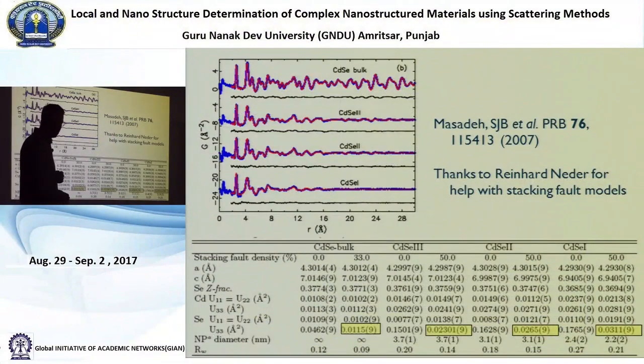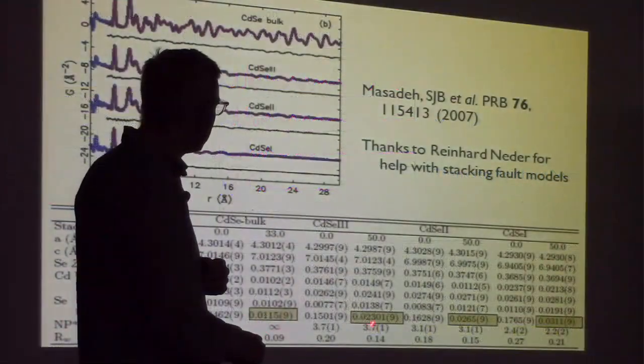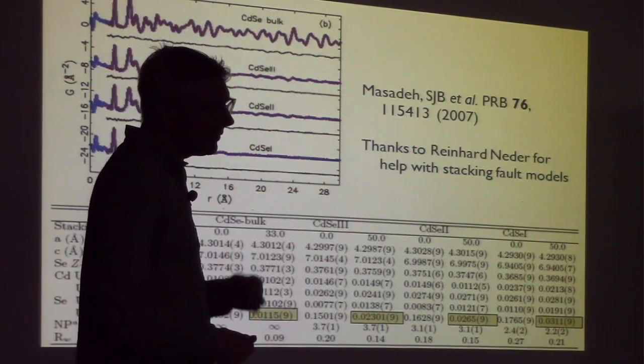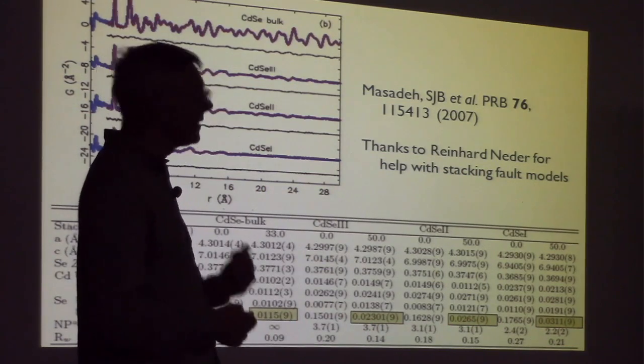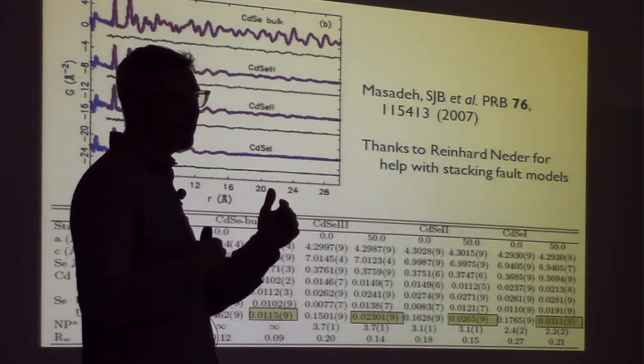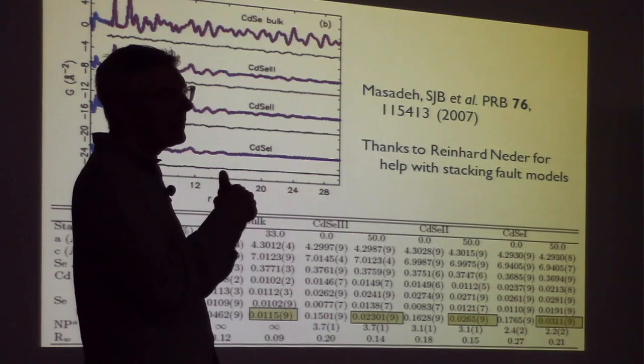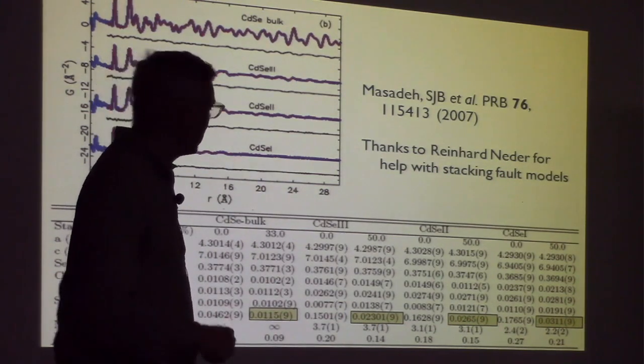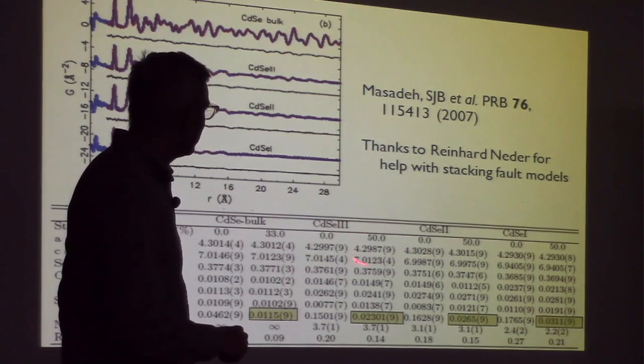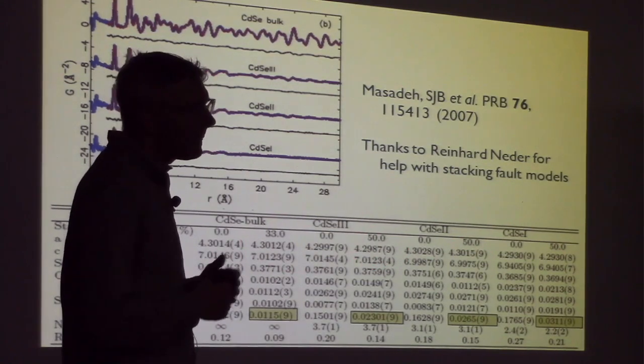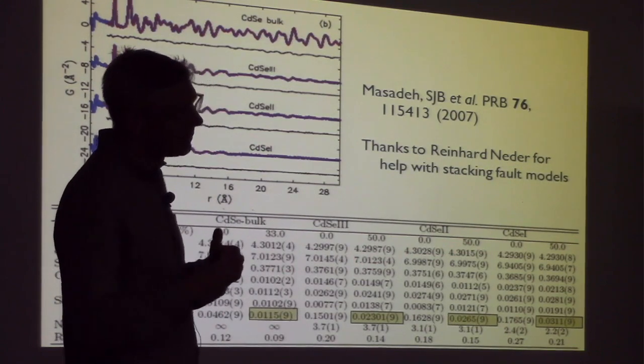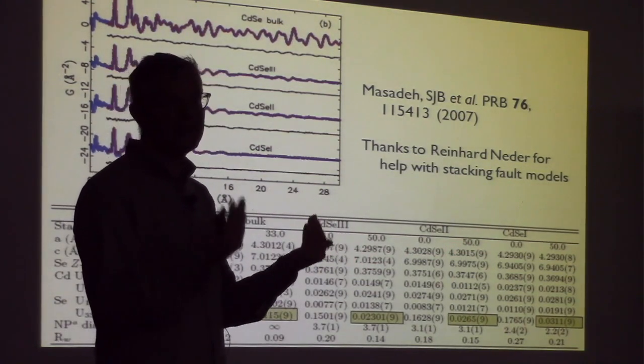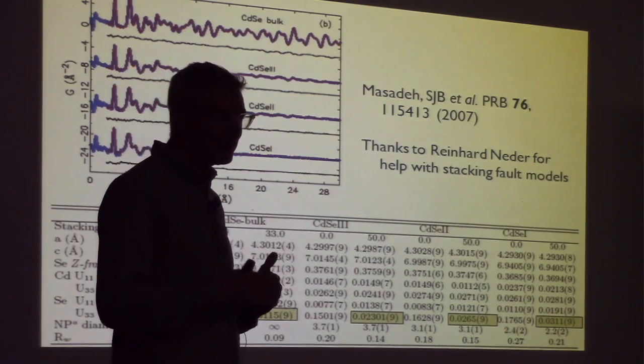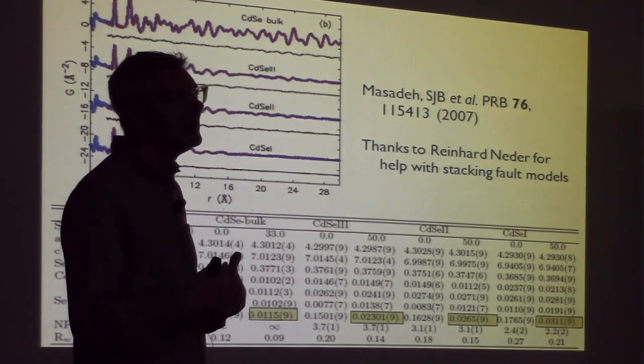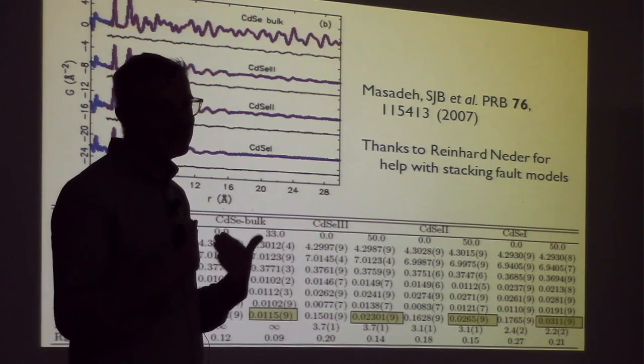But what we can do is make a model where we have the stacking faults in it. And when we have the stacking faults, then we refine this U33 again, we get good numbers. And we can also refine a stacking fault fraction. That is the probability of there being a fault. So it goes A, B, what's the probability of the next one being A or C? And we get very high numbers, like 50. I think these are overestimates. But 50% means that you go A and B, and there's a 50% probability of the next one being A or C. That means that these nanoparticle structures are completely confused, like they really don't know whether they're zinc blende or wurtzite. In fact, the distinction doesn't matter.